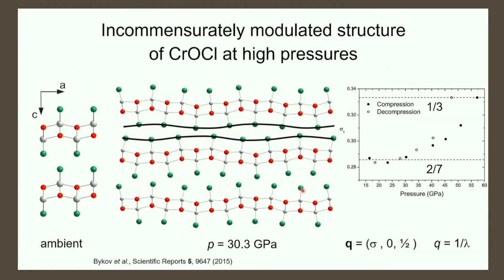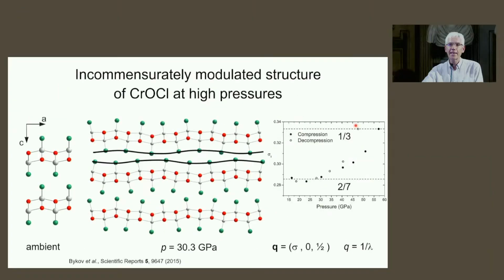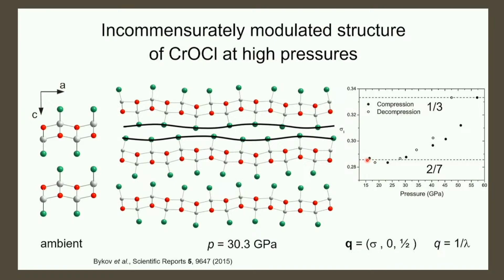Yeah, and this modulation wave is pressure dependent. Both the amplitude, which I do not consider here, is pressure dependent, and the wavelength or Q vector. So here going from 15 to 58 gigapascal. And as you can see, at high pressure, it first reaches this point, and then pressure is released. It stays exactly at 1/3, so one is inclined to believe here the modulation is commensurate 1/3, a 3-fold supercell. In between, here on increasing and decreasing pressure for filled and open circles, it passes many values, so one is inclined to say, yes, that is incommensurate, because there is no fixed value to a specific rational number. But at lower pressures, 15 to 25, it's about 2/7.